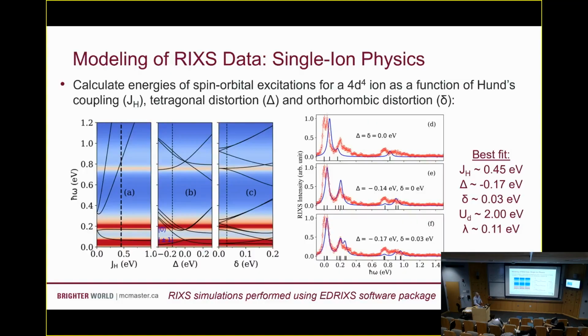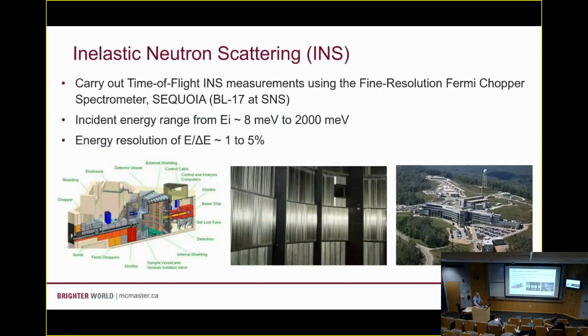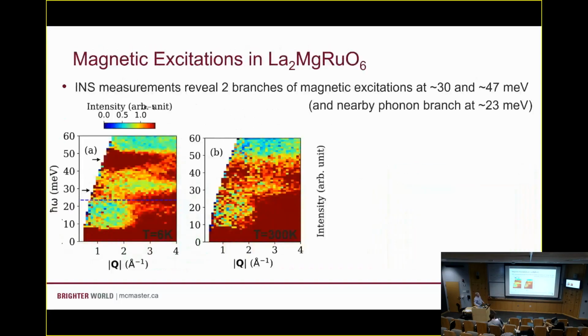Okay. I'll say we've done neutron scattering to get a higher resolution picture of this. These are measurements from Oak Ridge National Lab. We see, if we look more closely at this stuff going on below about 60 millielectron volts, something that looks pretty blobby up here on the screen, but I'm going to try and convince you that these are two magnetic features here.